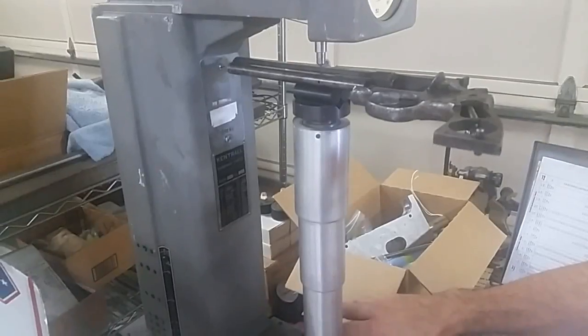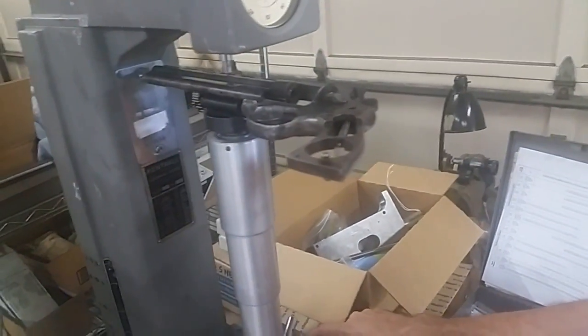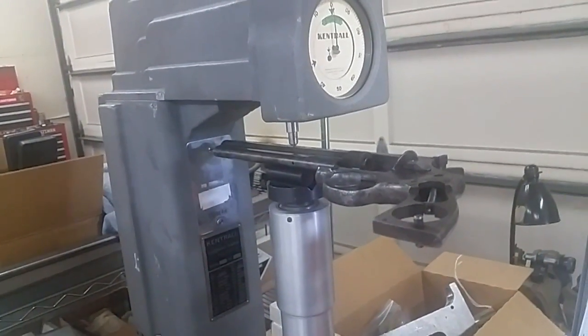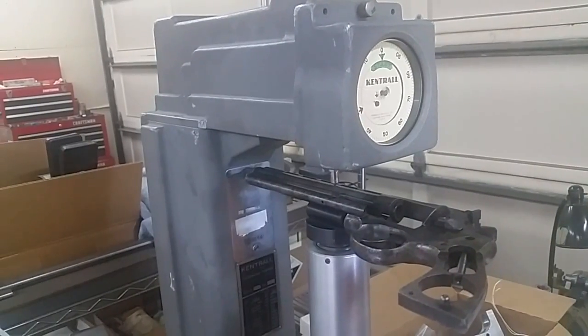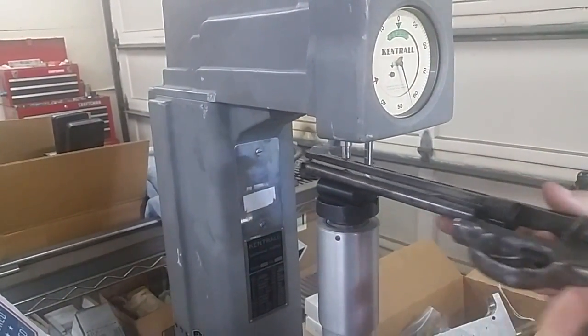Alright, stop recording. Zeroed out, trying it on the side of the barrel. Wouldn't recommend doing this on a gun that you care about the prettiness of. Now you've got 44. Barrel's testing at 44. In the general rule, you test three times and average the results together. 45, 45 - that's more in line with what I was expecting for a good gun. Teens were not good numbers. The barrel's testing at 44 to 45.